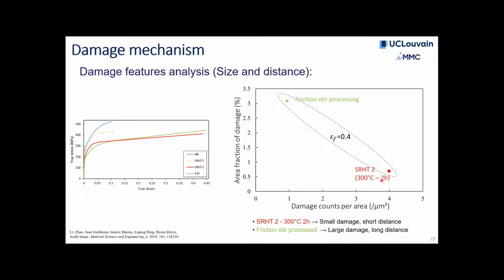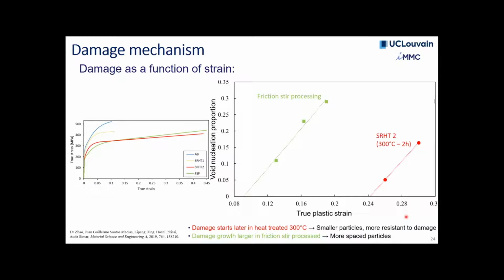So why do we have differences in nucleation conditions? Here is friction stir processing. Here is the stress relief heat treatment 2. And these were tested, and we had a look at statistics of area fraction of damage and damage counts per area. And what we can see is that the stress relief heat treatment leads to small damage, but at a short distance. So quite a lot of damage counts per area, so many situations of damage, while you have a lower area fraction of damage. And in the friction stir processing, we saw a lot of area of damage, but they're long distance, they're not very frequent. And this is related to the difference in the microstructure.